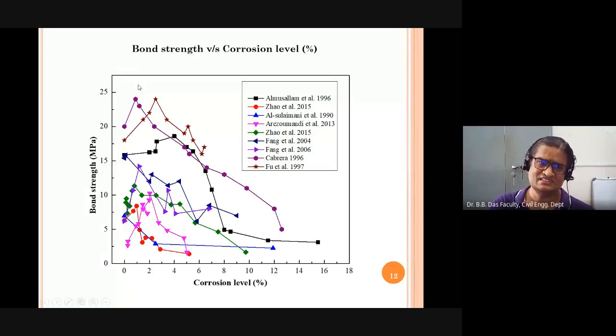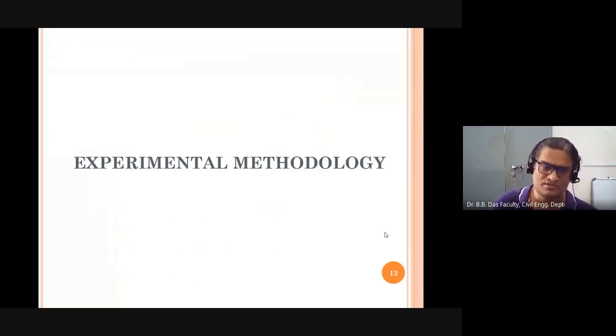You can see here a researcher where, at 1 or 2%, the bond is increasing from 20 to almost 25, but when the corrosion percentage increases, it comes down drastically. At around 10-12%, the bond strength becomes very low. So that is the mechanism, proving the mechanism of the corrosion cracking process. So let us move into the experimental methodology.